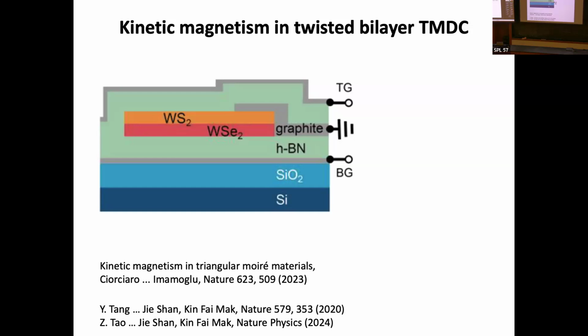What they observed was that if they hole dope the system, you get an antiferromagnet, while when you particle dope it, you get a ferromagnet. So the spin susceptibility depends on doping. Very interesting, maybe from a technological point of view. The other interesting thing was that these magnets were appearing at quite high temperatures compared to the expected superexchange in the system.